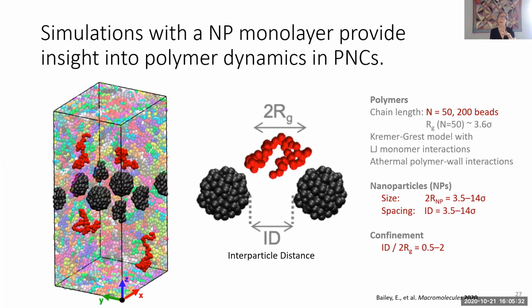So this is the same sort of coarse grain molecular dynamics simulations. We're using nanoparticles that are composed of a glassy packing of immobile particles. It's athermal, so the interactions of the polymers with the particles are the same as the interactions among the polymers. We're mostly going to do this with the shorter chain because the 200 bead chain just took a lot of computational time.